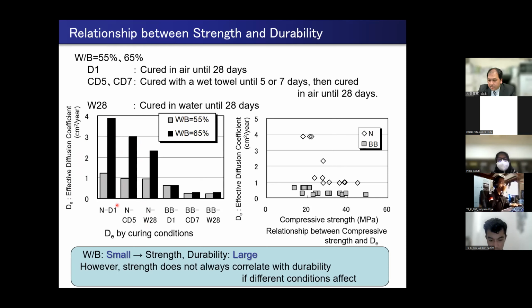Here, ND1 indicates that it was cured in air until 28 days. CD5 and CD7 were cured with a wet towel until 5 or 7 days, then cured in air until 28 days. And W28 indicates that it was cured in water until 28 days. Even if the same concrete is used, if the curing condition is different, then the durability of hardened concrete also becomes different. Curing in water until 28 days shows the best performance.